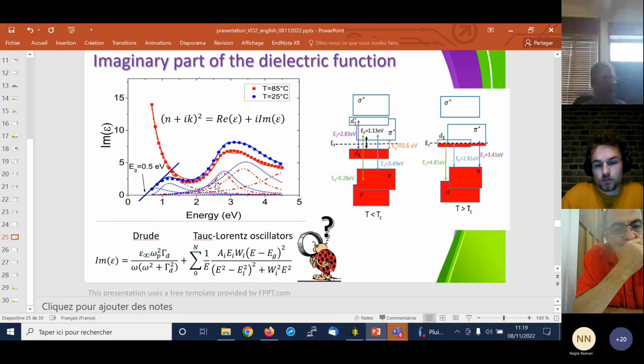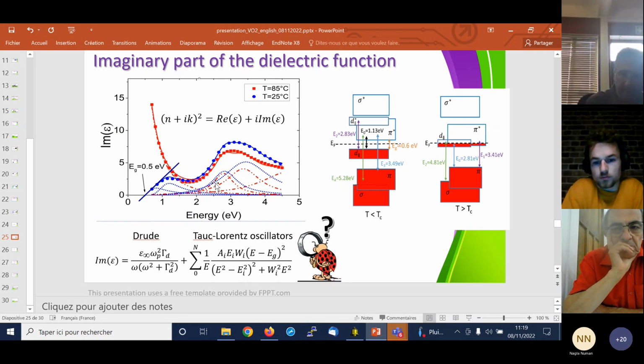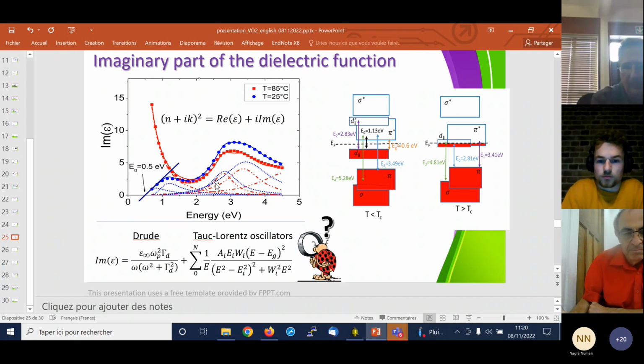And just also to give you more information about the point by point, if you put the wrong thickness, you will not get it right. The point by point is also very interesting because since you are getting the N and K values for each wavelength, if you make a mistake, you will not get a smooth curve for N and K. You will get some kinks inside the calculated N and K, and sometimes, I mean, it's completely crazy. So we tested that, playing a little bit with changing the thickness of the film, and it's very sensitive also in the point by point method. But to come back to your question, yes, we measured the thickness in both phases. And there was not a big difference between the two thicknesses.